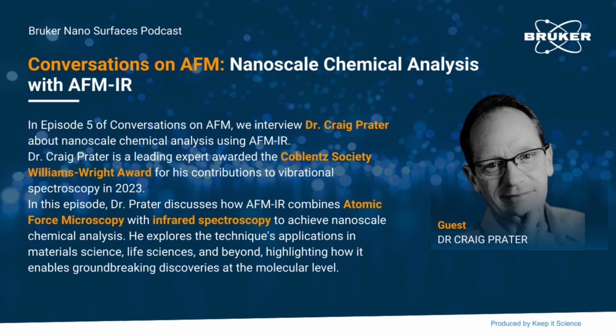You also briefly mentioned now that AFM-IR and OPTIR are complementary and can be used as complementary tools or technologies. Could you maybe explain an example where that would be useful and maybe what some challenges could be when you try and do this? Well, I touched on one of the application areas, and that is related to, for example, different scan sizes. So AFM, of course, is the clear leader for obtaining the highest possible spatial resolution. But when one has to scan an AFM tip over a large area, that becomes prohibitive in terms of time. Where the OPTIR's coarser spatial resolution can let it cover larger areas of the sample faster.